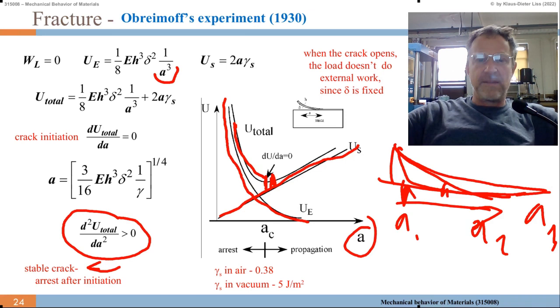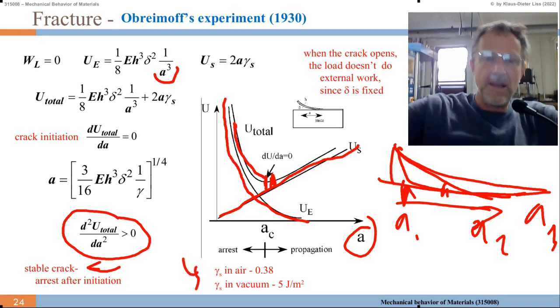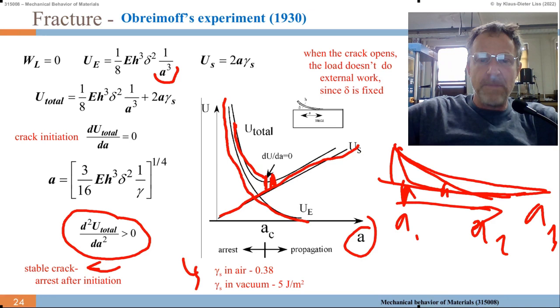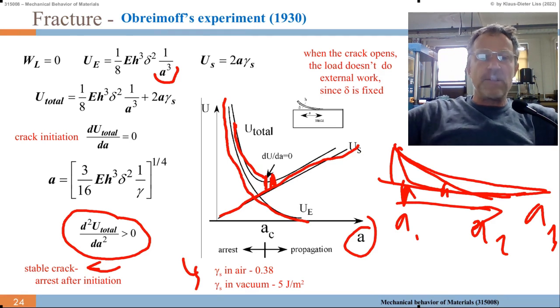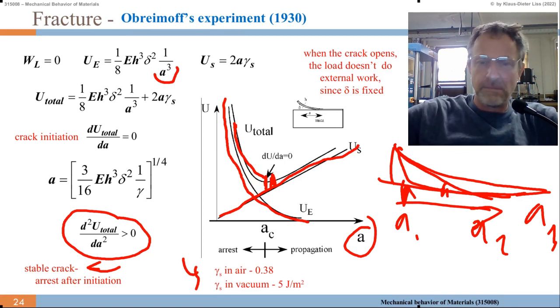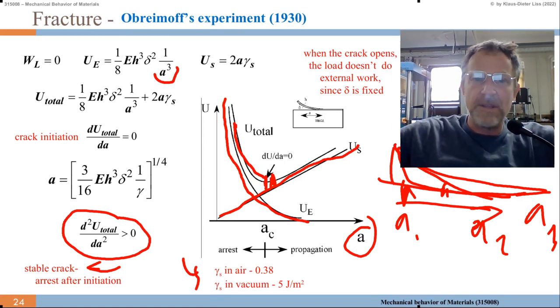Here are some values. Gamma S in air is 0.38 joule per square meter, and in vacuum it's 5 joule per square meter. So it also depends whether you do it in air or in vacuum - air can push a little bit into the crack and push the atoms apart.